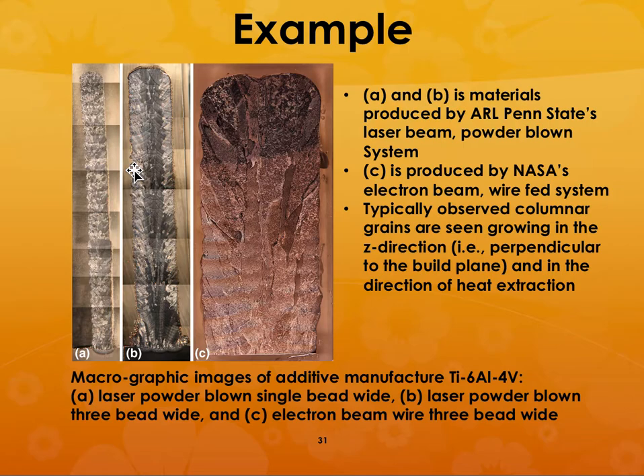In this case, the materials are produced by Applied Research Lab at Penn State. It is done by laser beam melting, and it's called the powder blown system. And the third one is produced by NASA Marshall's electron beam wire fed system. In all these cases, you're going to have some kind of columnar grains, and there could be more columnar grains in one type than the other due to the heat extraction in one direction. So heat is going to be extracted in the direction of the nozzle movement.